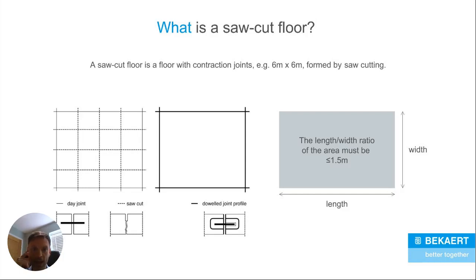Here's a little example here. On the left hand side, you'll have a grid of saw cut joints, say on 5 or 6 meters. It's a small sample that you can see on the screen there, but if, for example, they were at 6 meter centers, you would have a panel there on the left of around 600 square meters. But you can see you would have a network of over 140 linear meters of saw joints. That's important to know in a few slides' time.